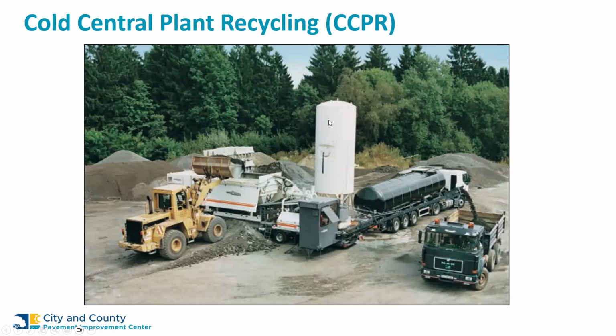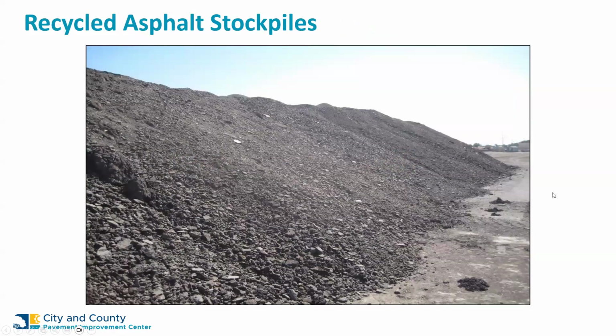We have cement here for our active filler. We have asphalt, either hot oil or emulsion, that we can add to it. And then this process just churns it out and typically throws it back into the truck that just brought the RAP millings, and it goes back out to the project and is paver laid like you would do with hot mix asphalt, which opens up a new area as well.